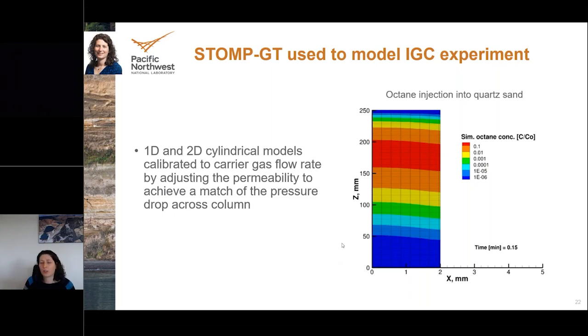And what we started simulating is the octane injection into quartz sand. The different colors in this model indicate the different octane concentrations. The red in this case is the highest concentration, and then you can see lower concentrations on either side of it. So if this were to reach the detector, you get a nice peak.